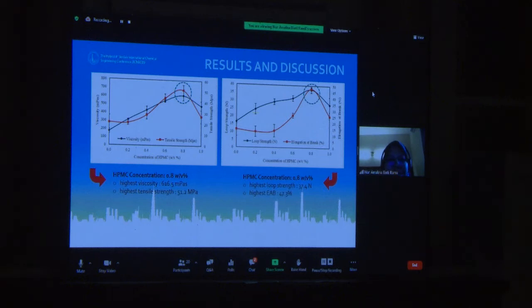In the left figure, the presence of HPMC causes the viscosity to increase significantly, with its highest point achieved at 0.8. And the tensile strength, elongation at break, and also the capsule loop strength are also significantly improved to their maximum at the same concentration. However, a higher concentration of HPMC in the carrageenan matrix causes agglomeration, and disturbs the intermolecular interaction between carrageenan and HPMC. Thus, it reduced the viscosity of the biocomposite. At this point, the increase of HPMC most likely does not result in higher tensile strength because the maximum ability of the film to restrain the applied load is reached.